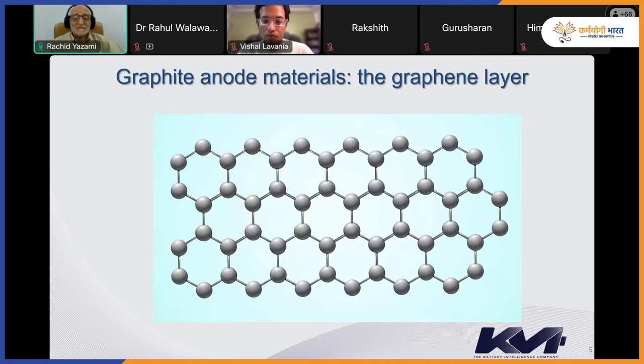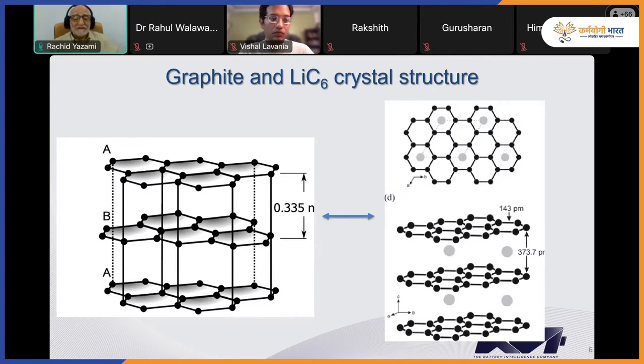And the next slide shows the three-dimensional graphite structure, where on the left hand we have layers of graphene stacked on top of each other, with a sequence of AB, AB, or ABC, ABC. I don't want to enter into the detail, but this is the crystal structure of graphite, the hexagonal graphite, which is the one shown in the left-hand figure. On the right hand, you have the structure of the lithiated graphite with the composition LiC6, which means that every six atoms of carbon host one lithium. This is the average structure.